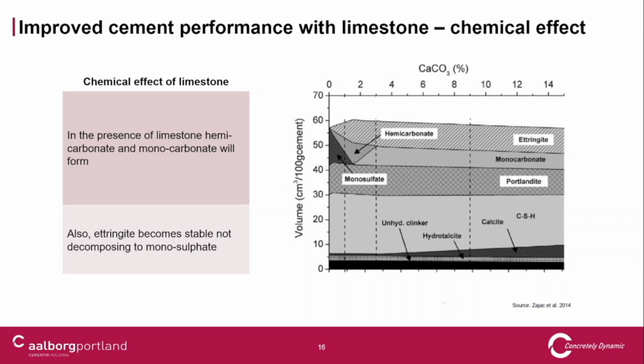The chemical effect is that a small part of the calcium carbonate will dissolve and react with the aluminum phase in the cement, forming what is known as hemicarbonate or monocarbonate. This somewhat complicated graph shows the amount of carbonate in the system and which minerals are formed. This is a slow process, so it happens after weeks, but before 28 days.